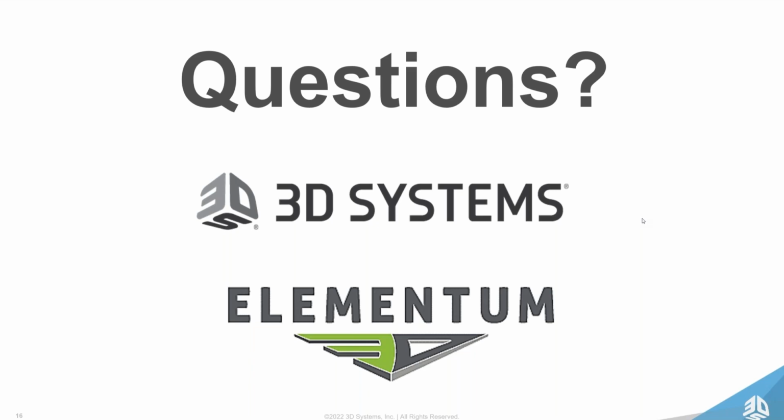Great, thank you. Our next question is, how does build productivity look versus other materials so far? So relative to our LaserForm AlSi10Mg on the Flex 350, 6061 is probably like a 5 to 10% increase in productivity, but by no means is our parameter set optimized at this point. And that's actually going to be the next coming months, specifically to improve that productivity. In fact, Aaron ran a couple productivity DOEs yesterday.